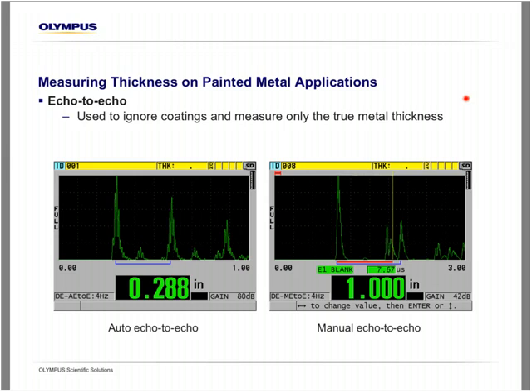So automatic echo to echo will automatically make thickness measurements between the highest amplitude backwall signal and the second highest amplitude backwall signal, as you can see on the left. Whereas on the right, we're doing a manual echo-to-echo. So in this mode, the user has the ability to make internal adjustments. So they have the ability to adjust blanking to eliminate any signals or shear wave components that are present between the two backwall signals. So both are a pretty automated measurement. The manual echo-to-echo just gives you that extra adjustment if automatic doesn't work.